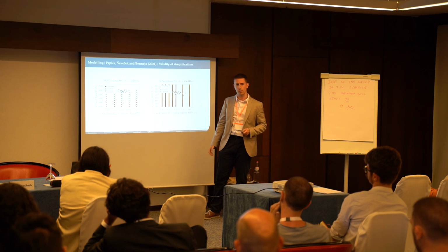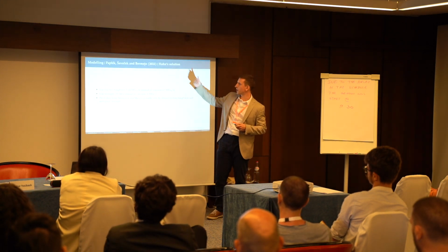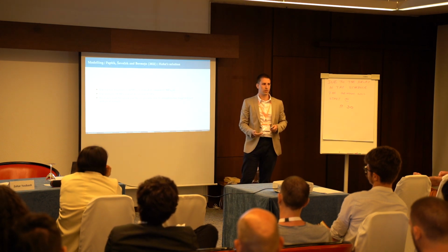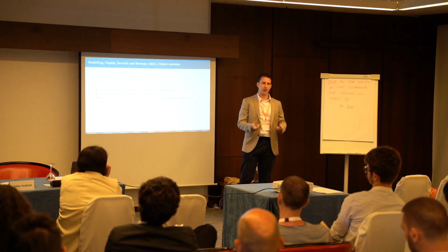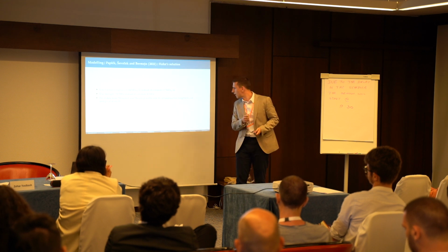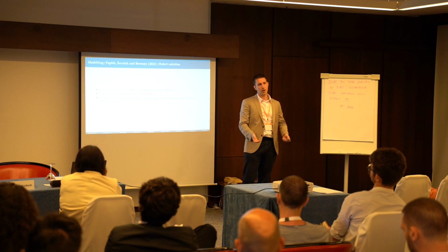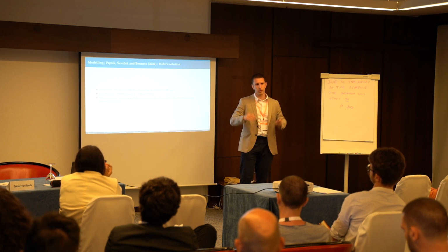And then I looked into the publication of Hahn, and his explanation was, let's just increase the fracture toughness by 2 and make the strength of the glass instead of 90 almost 800, which is not acceptable for us. So maybe we don't see the whole picture, and we need to get more experiments.